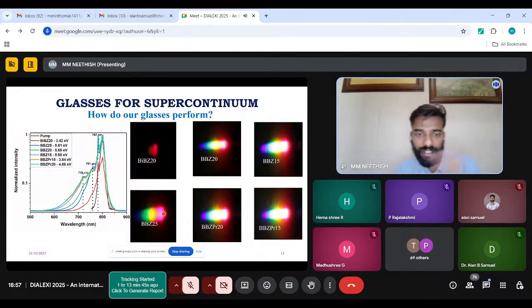You don't need a spectrometer or an instrument like this to see the difference, you can see it. So it's quite evident that by tuning the material, you can tune the color of light you want, which is very important in the sense that, as I was saying before, you need to have a pump and probe in a region where you have something happening. If your material is doing something in green light, you have to have some light in green. If you go with the red, you will not see anything. So this is very important.